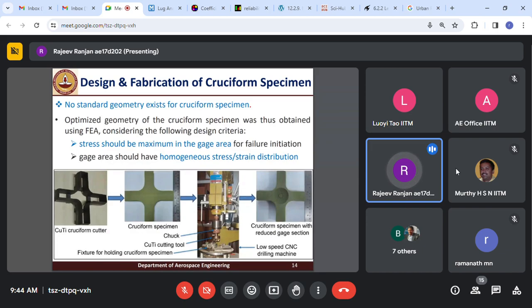In order to do the biaxial test, the first step is to design a cruciform specimen for composite solid propellants, because there was no standard geometry for that. In order to get the optimized geometry of the cruciform specimens, we considered two design criteria. First, the stress should be maximum at the gauge area so that the specimen fails there. That is necessary because only then will we be able to capture the behavior of the material up to failure. Otherwise, one of the biggest problems in conducting biaxial tests is the failure of the arm of the specimen. In order to avoid it and fail the material at the gauge section, stress should be maximum at the gauge section. And the second design criterion was that there should be homogeneous stress and strain distribution at the gauge section.